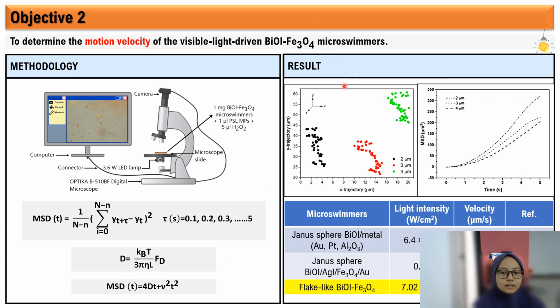This figure shows that the microswimmers move forward in the y-axis and left and right in the x-axis, exhibiting translational propulsion. Moreover, the mean square displacement plot shows a parabolic curve that indicates the nonlinear motion of the microswimmers. This table shows that the bismuth magnetic microswimmers can move at a reasonable velocity at lower light intensity as compared to previous studies.